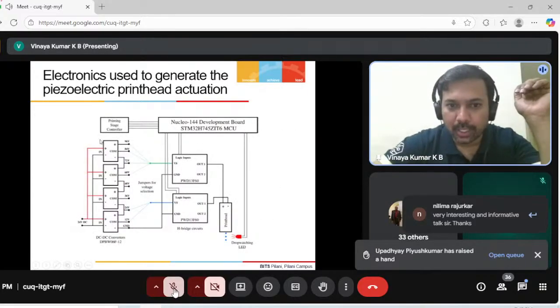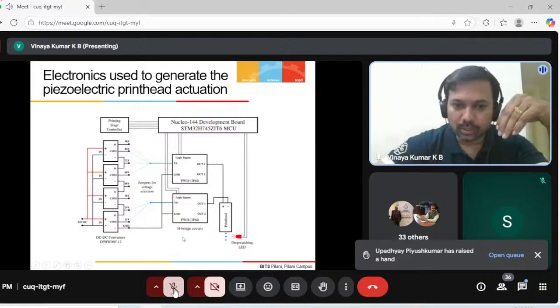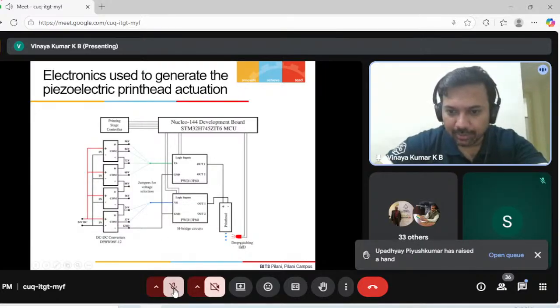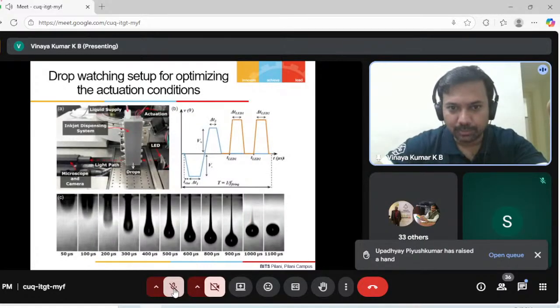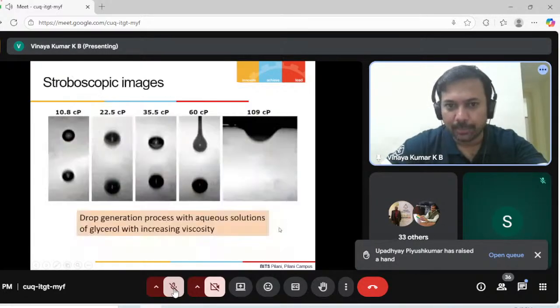And also we built the required electronics, because like I said, once you have the device, you need to calibrate it or actuate it. As it is printing, we were able to hack one of our in-house printers. We were able to generate and observe the drops for different voltages and different conditions of the ink we were printing. Something similar to this. This is the complete setup, the in-house built print head, assembled, and the voltage pulses are applied to the piezoelectric material. As you can see, with respect to different time, how the drop generation is happening.